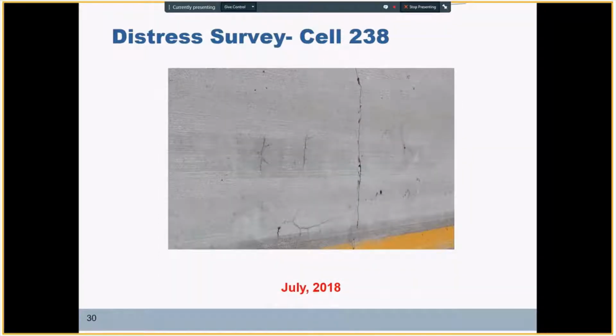However, after a short while, we noticed increasing cracks - here I have a better picture. We have these spider-like cracks forming adjacent to that wide open transverse crack. The first time we noticed these was July 2018, about 5 months after the initial crack formed. So it was interesting for us to find the reason for this cracking.